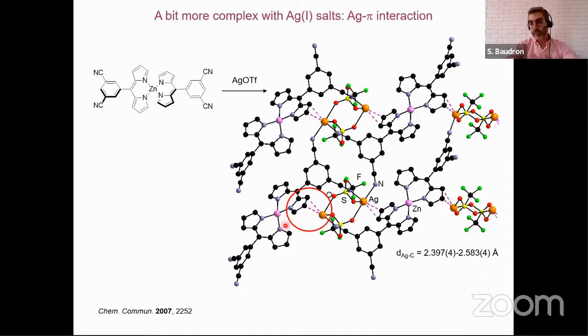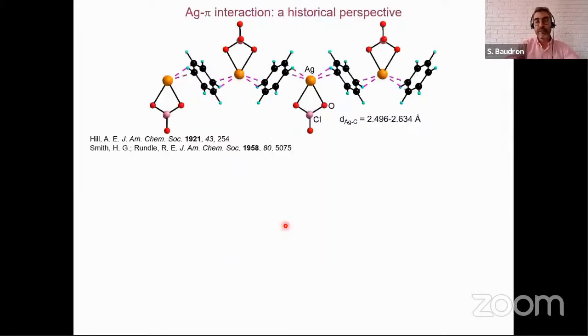So this was unexpected for us, although silver-pi interactions per se are not a novel interaction. Actually, they were suggested about 100 years ago by Hill when he was trying to determine the molecular weight of silver perchlorate in benzene. What he obtained were surprising results, and he suggested back then that there was a specific interaction between the benzene ring and the silver cation. This was later confirmed by Smith and Rundle in 1958 when they determined the crystal structure of this material, indeed highlighting that the silver sits on top of a carbon-carbon double bond with a distance of 2.5 to 2.6 angstroms once again. This was later heavily investigated in the literature with a whole variety of aromatic and polyaromatic systems.